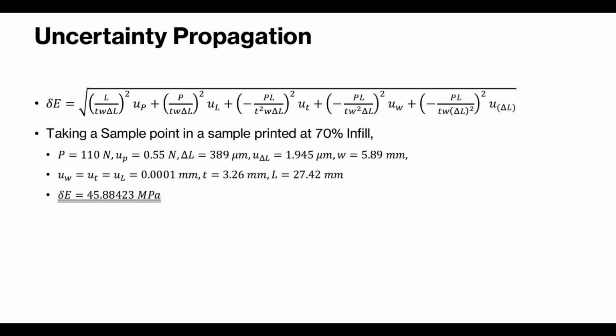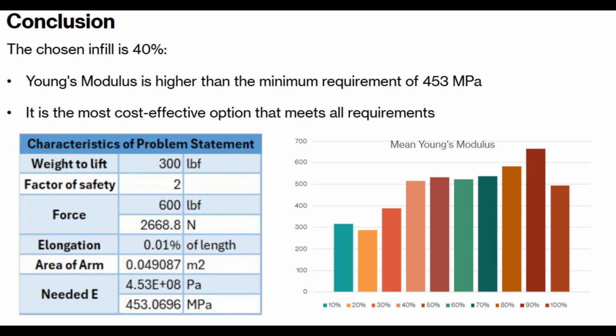The uncertainty propagation of this sample was found by using the sensitivity equation, or the root sum square, of all of the partial derivatives multiplied by the associated uncertainties. Using a sample point printed at 70% infill, we found that the propagated uncertainty was equal to 45.88 megapascals. This was consistent with the values found using the z-table. Therefore, we can conclude that the z-table values are accurate and can be used along with the student's t-test and Chauvenet's criterion.